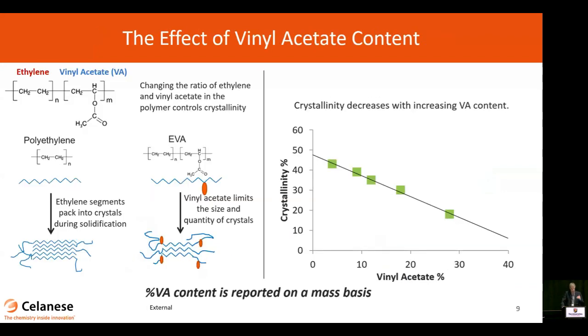So the parameter that becomes very important for understanding long-acting drug delivery systems with EVA is actually the vinyl acetate content of the material, or the ratio of the ethylene and vinyl acetate in the polymer itself. And typically this is going to be reported on a mass basis of vinyl acetate. The reason why this is important is that polyethylene is a material that readily and easily crystallizes quite rapidly to a quite high degree of crystallization.